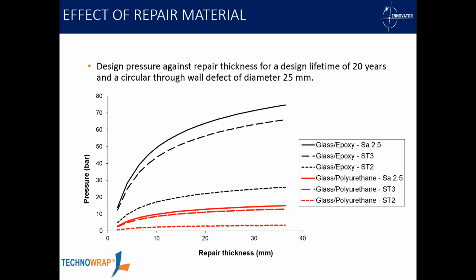This is where a lot of the misinformation and perception of it being a temporary repair comes from, what I've seen particularly in Canada and the United States. This is where this reputation and misunderstanding has come from. The combination of using polyurethane or these water activated products, what I will call a pipe fitter wrap, along with hand preparation, and then people say, well, they don't work, they just slow the leak down. And that's because they don't work. They're not a good solution.